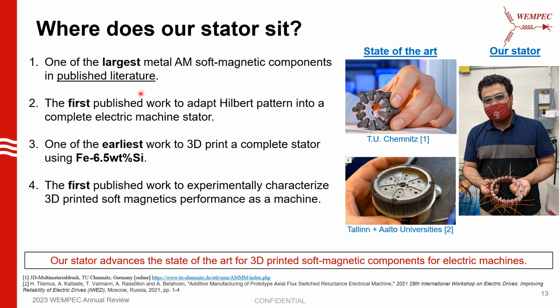Well, our work is one of the largest metal additive soft magnetic components in published literature. It is the first published work to adapt Hilbert pattern into a complete electric machine stator. It is one of the earliest works to 3D print a complete stator using 6.5% silicon steel, and it is the first published work to experimentally characterize 3D printed soft magnetics as a machine.